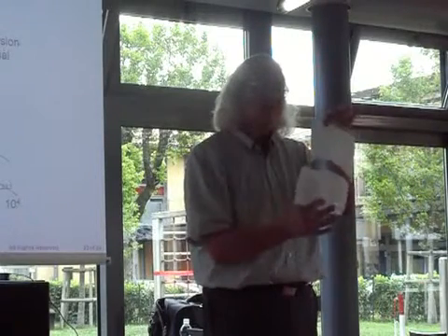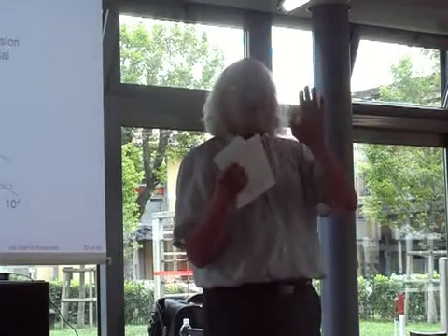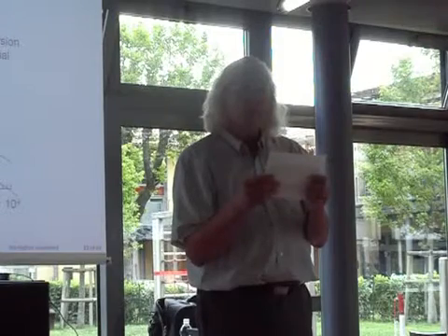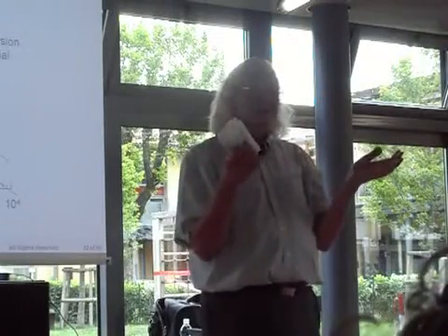How can energy ever work? Because we know the fundamental physics is there's lots of little cracks in there, and little cracks are planar in nature in certain directions. So the energy models are doomed from the first physics. They are just doomed to failure. Energy models are usually proposed by people who've not been in the lab to see what happens, people who only like to do calculations. But energy models just don't work very well, and they never will.